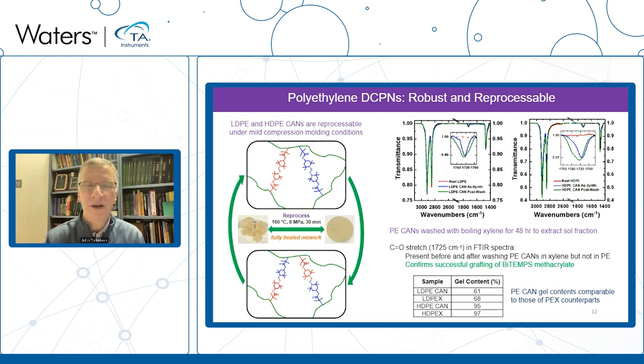We know based on spectroscopy that we actually have this BiTEMPS methacrylate linked in as the linkers in these cross-linked systems. So we've done work where we've removed any linear material in the system after doing the cross-linking by using Soxhlet extraction to remove the sol fraction and just to characterize what's there in the cross-linked systems. And we have characteristics here associated with the BiTEMPS methacrylate in these systems.